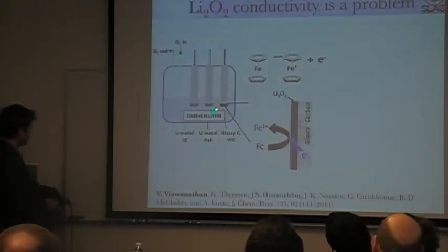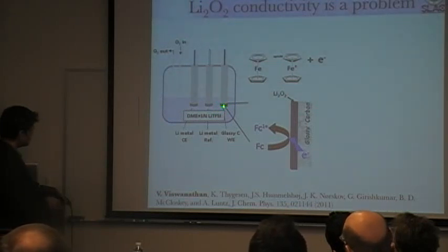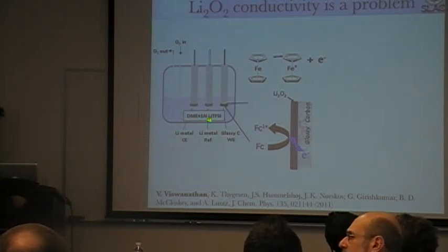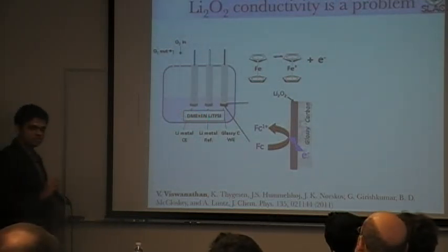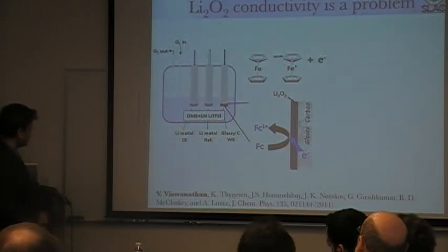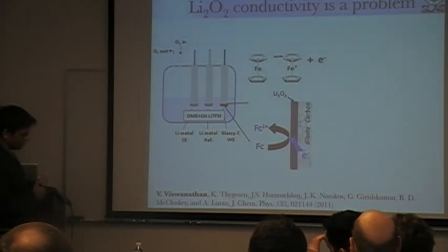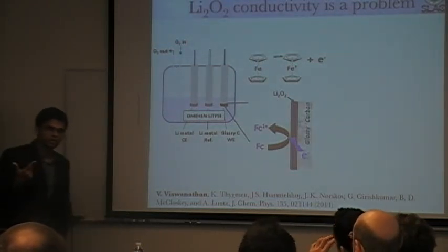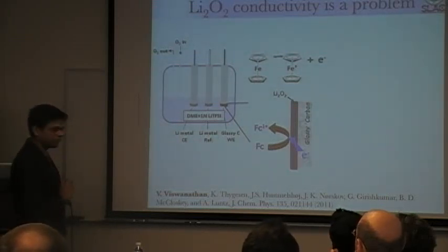And so this is what our collaborators at IBM did, where what they looked at was in a bulk electrolysis cell. Here you have one normal lithium TFSI, so you have abundant lithium plus transport and it's rapidly stirred, and then you have oxygen dissolved, so there are no mass transport limitations associated with oxygen, and no ion transport limitations associated with lithium plus. The only other thing that is there is electrons.